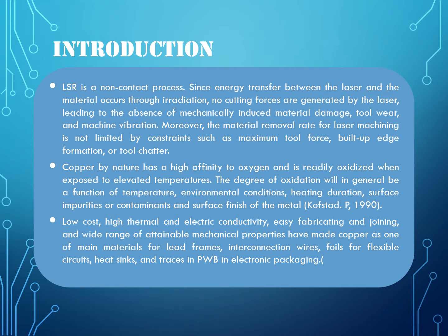Introduction. LSR is a non-contact process. Since energy transfer between the laser and the material occurs through irradiation, no cutting forces are generated by the laser, leading to the absence of mechanically induced material damage, tool wear, and machine vibration. Moreover, the material removal rate for laser machining is not limited by constraints such as maximum tool force, built-up edge formation, or tool chatter.